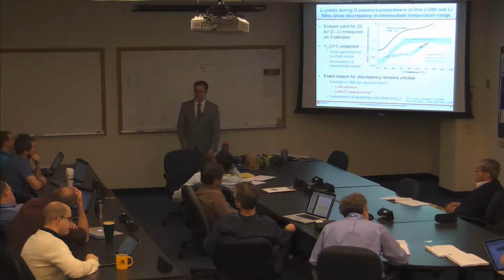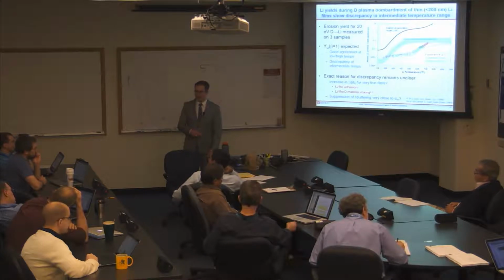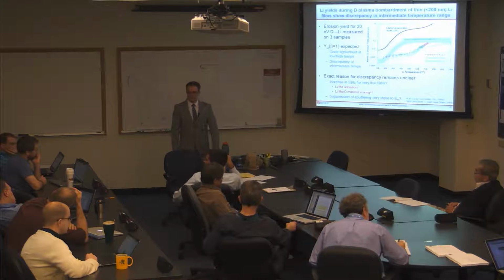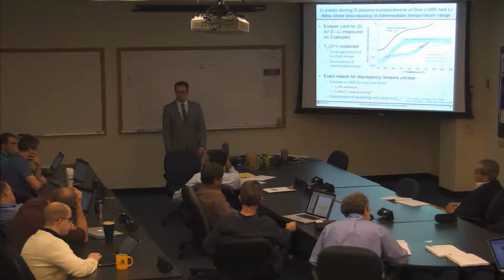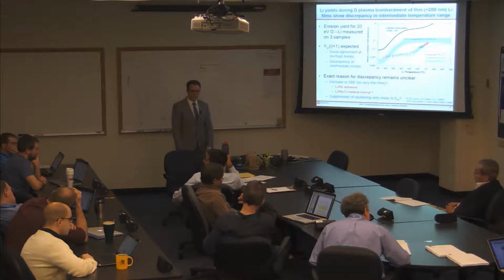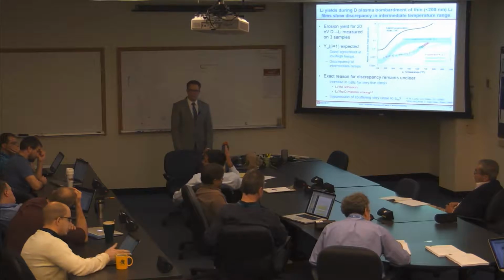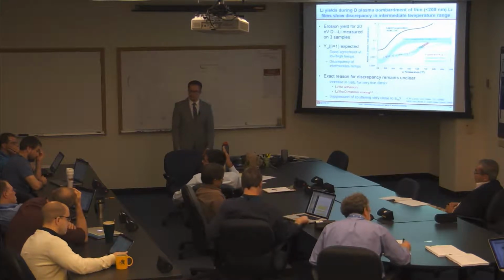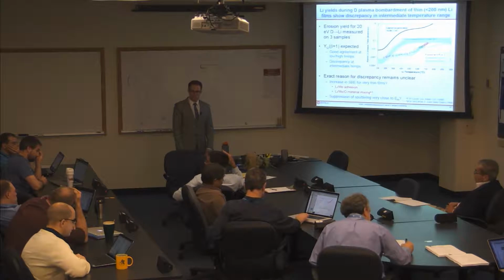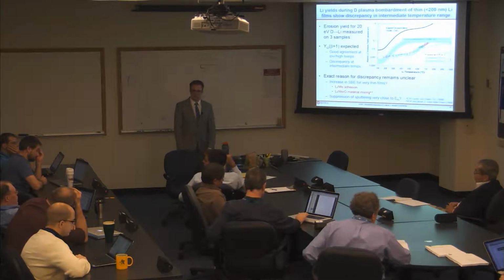Okay. Yeah, maybe we can talk about this later. Keep in mind that this is a lot higher background pressure than your experiments. So the first time we did these experiments with a much lower flux evaporator, there's a lot more oxygen in the films, and we did see oxygen emission in the plasma during those experiments. But then when we switched over to the lithium evaporators, which have this huge flux compared to those small ones, it was pretty clean.